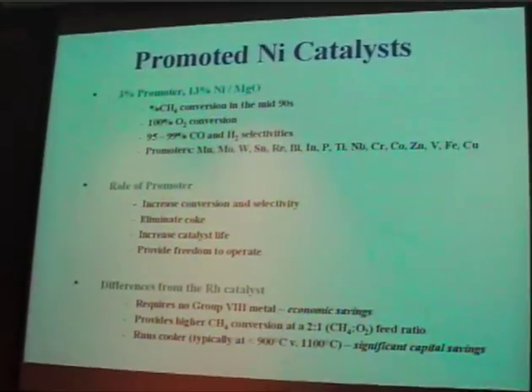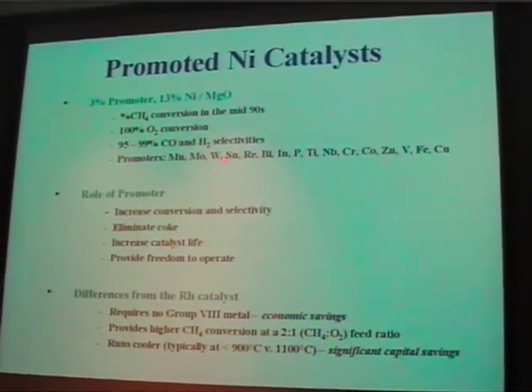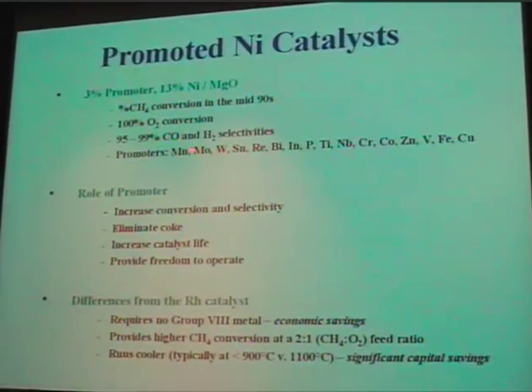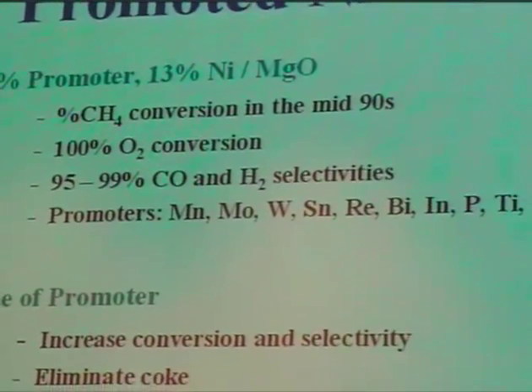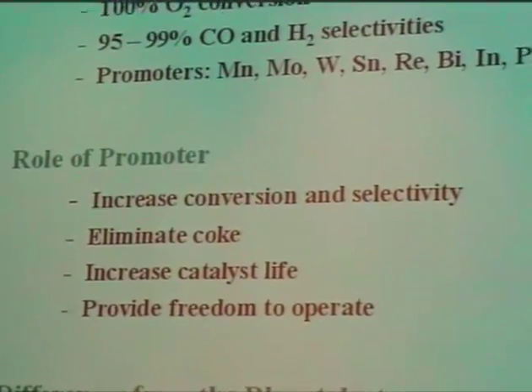So we investigated a number of promoters. These are the ones that were claimed in the DuPont patent. Some of the better ones, the first 3, you'll see the patent data on that. But basically the role of the promoters, it would enhance conversion selectivity, essentially eliminate problematic coke, enhance the catalyst life. And it also gave DuPont freedom to operate because there was already in the open literature nickel on MgO.